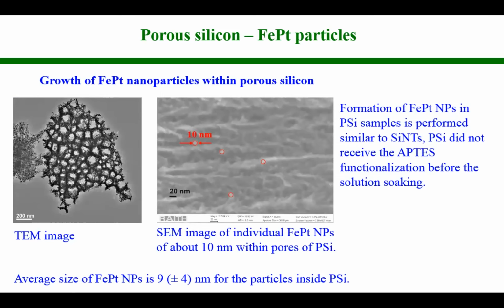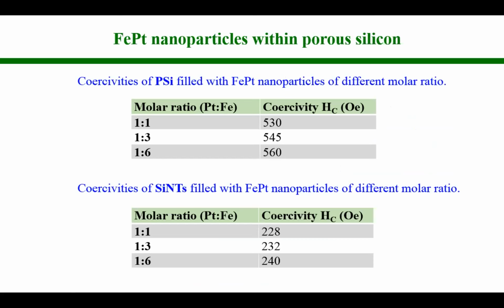So this here is coercivity data of various molar ratios for a porous silicon sample, and coercivity does not vary in a broad range. The deviation is about 5%, and this is in both cases the same.